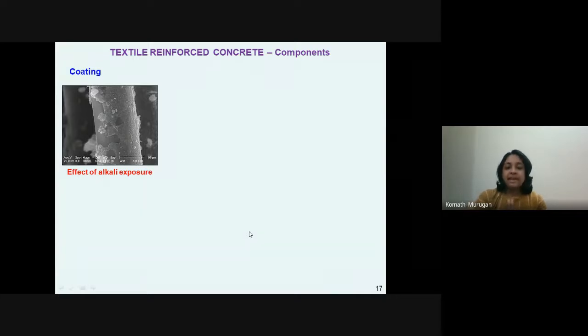So now that we have the fibers which formed the filaments, which formed the yarns and the textiles, if we use these textiles directly in the alkaline environment of concrete, the glass of which these textiles are made gets affected by the alkali present in the cementitious environment around, and it tends to dissolve and deteriorate in strength or properties, due to which they show a much reduced lifetime or behavior. This is called the effect of alkali exposure, which we can see here in the microscopic image, where there is glass dissolution due to the exposure of these direct glass fibers in the alkaline environment.